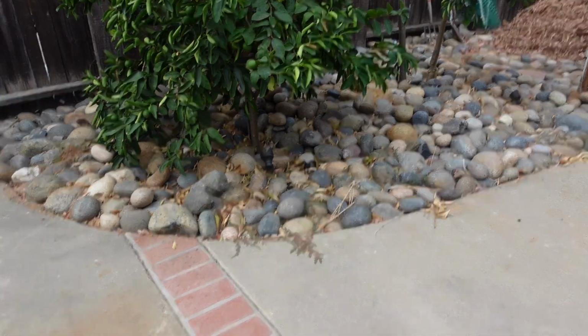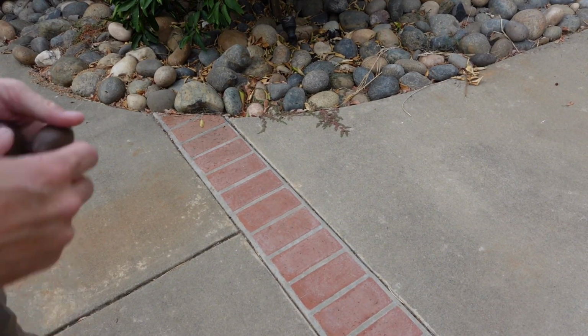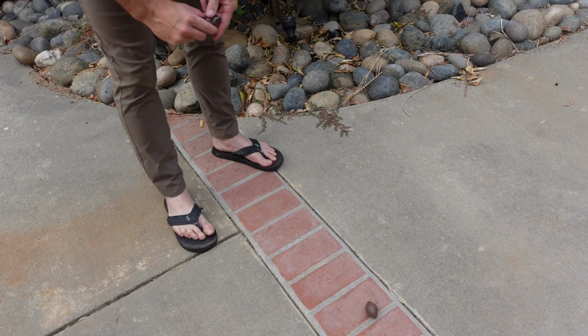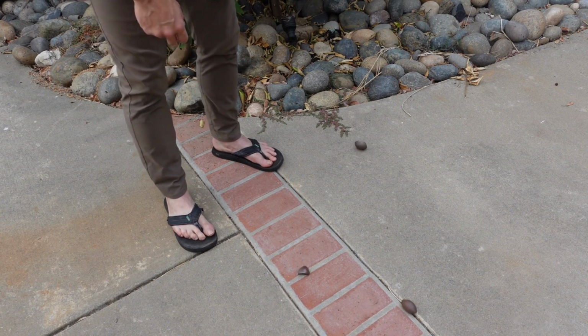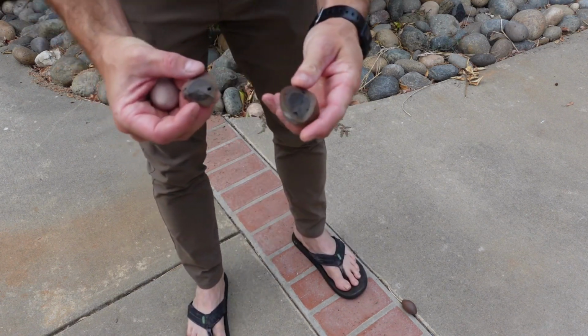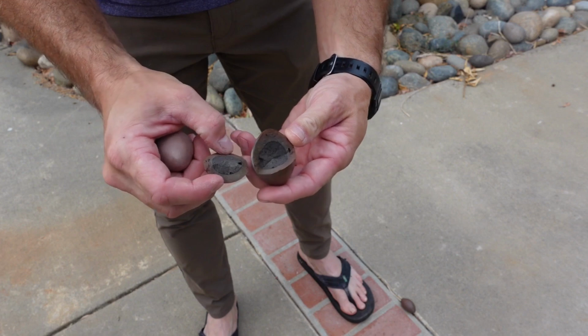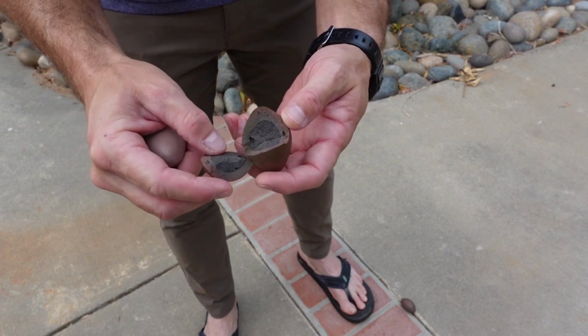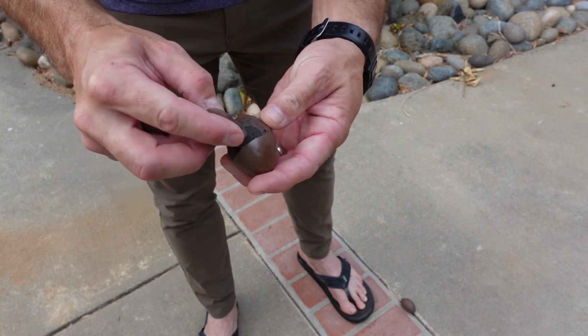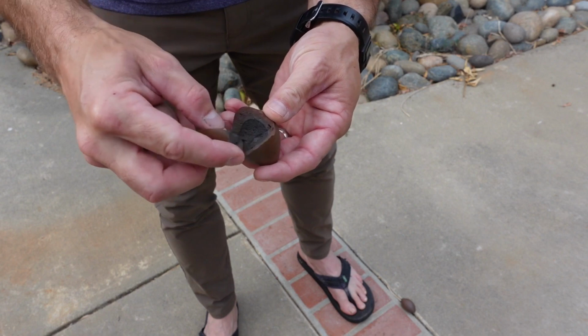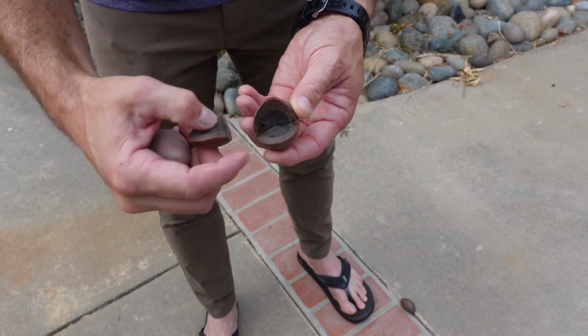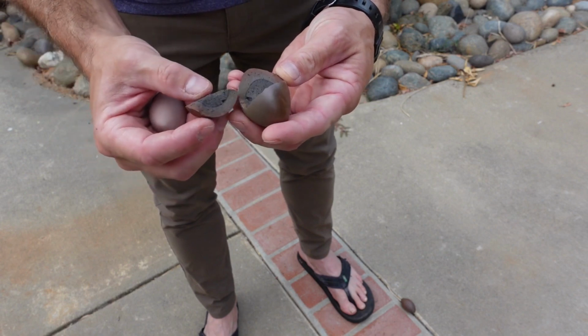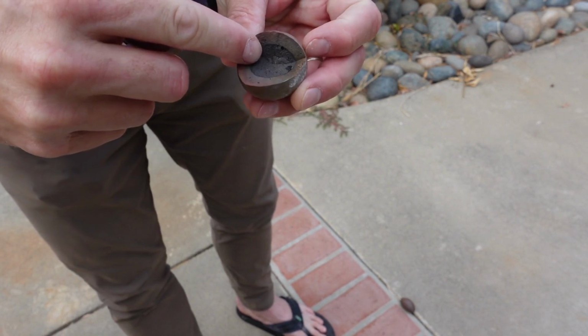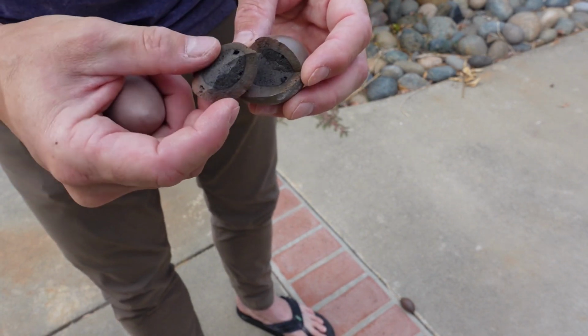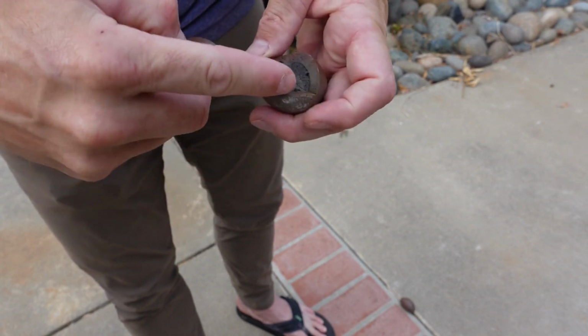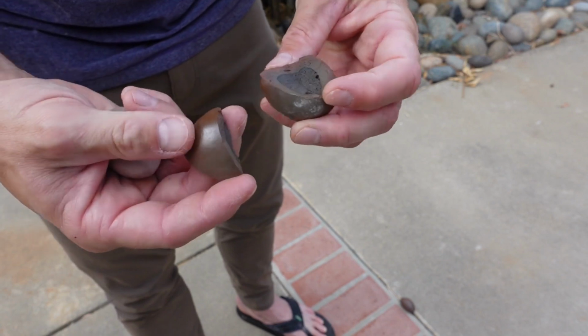Just a quick demo on how dense these balls are after firing. So if I soaked this for a longer time at high temperature, I imagine we would have got a better firing, better sintering in the middle. You can see that the outside is nice and dense, the middle's less so. And there's lots of little air pockets, and that's partially because of the densification. It's also partially, ooh, look at that guy. There's a big hole. There are some air voids in here. So I got lucky these didn't blow up to begin with.